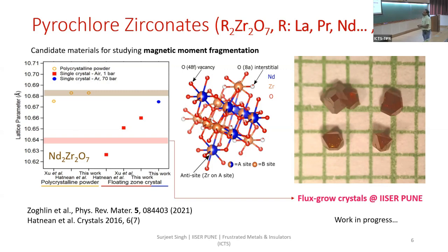And if you grow crystals under ambient pressure, you get a lattice parameter which is much smaller, which indicates that some of your neodymium is gone, which is the bigger ion, and it has been anti-stuffed by zirconium. So they have grown these crystals at various pressures, and under 70 bar pressure, they come very close to the ideal lattice parameter.